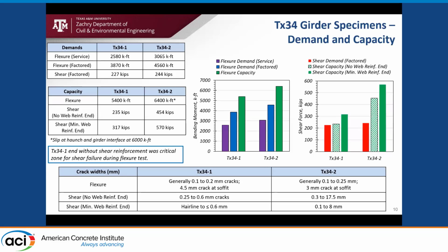The cracking was also very limited, and under service condition, we got no cracks. Beyond the factored demands, we observed slight hairline cracking. At failure, we only had major cracks at the crack localization areas, with a 4.5 mm crack and 3 mm crack for the two girders respectively at the soffit where the crack occurred. For the no web reinforced end, we observed wider cracks under shear with more crack opening near the failure. For the minimum web reinforced ends, we had quite narrow cracks until the major crack opening.